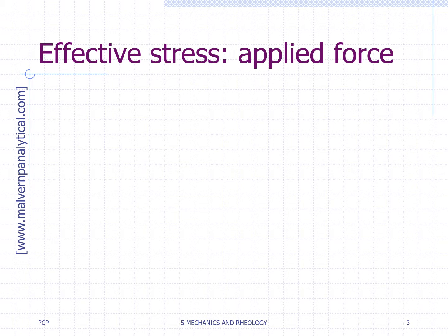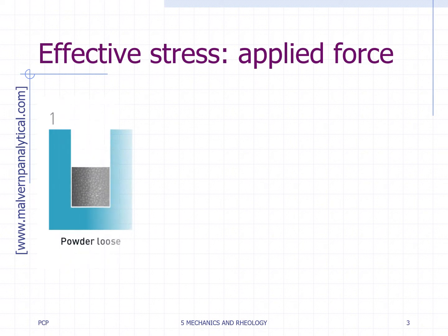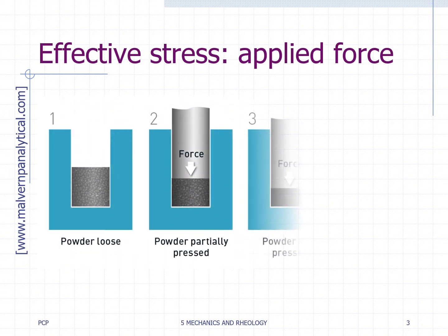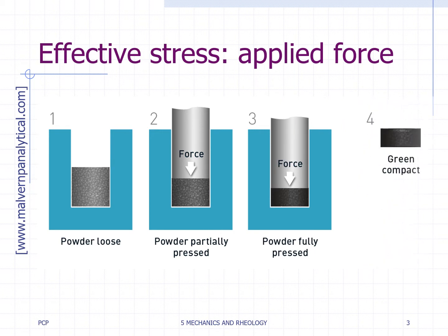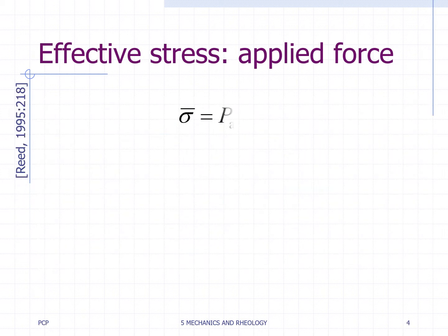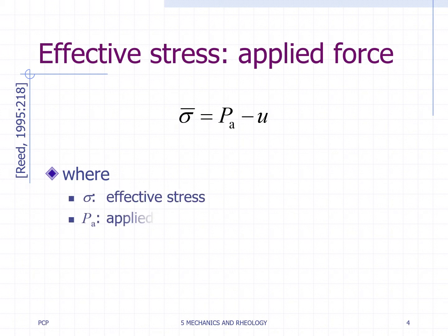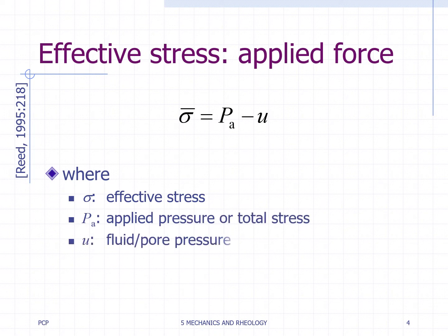Ceramic bodies containing a pore phase incompletely saturated with a liquid can be deformed both elastically and plastically when compressed. For those materials, the resistance to deformation is dependent on the cohesive strength and the frictional resistance between particles. When an unsaturated particle system is compressed, the imposed pressure is supported by the mechanical stress at particle contacts and by the pore fluid pressure. The difference between the applied pressure, Pa, and the fluid pressure, U, is called the effective stress, sigma.